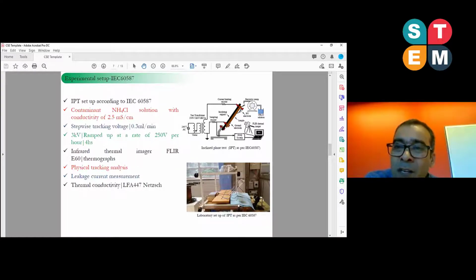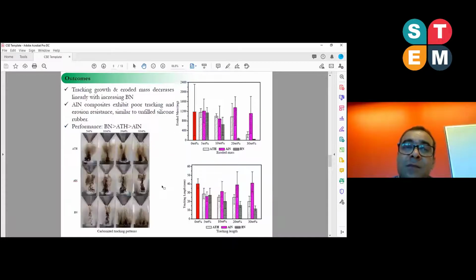Here is the ammonium chloride solution. We have to feed the ammonium chloride solution here on the top HV electrode. HV is connected on the top electrode. The bottom one is connected to the ground. Here is the infrared thermal imager to capture the thermography, the temperature on the surface of the insulation. In the meantime, we have to measure the leakage current as well. So this is a laboratory setup. We have to capture the thermal images. At the end of the experiment, we will measure the physical tracking and erosion. We have to measure the leakage current, and separately we have to measure the thermal conductivity of the insulation as well.